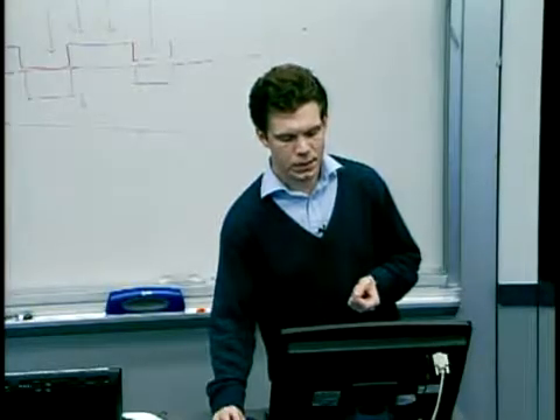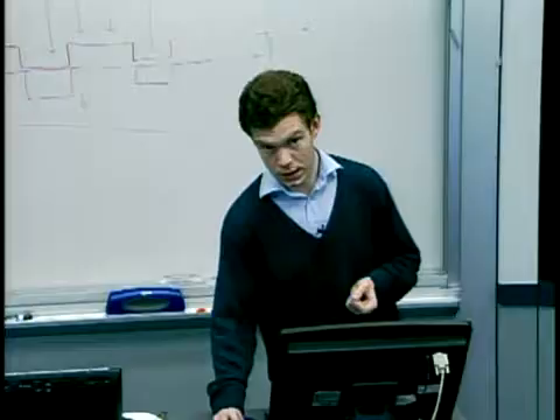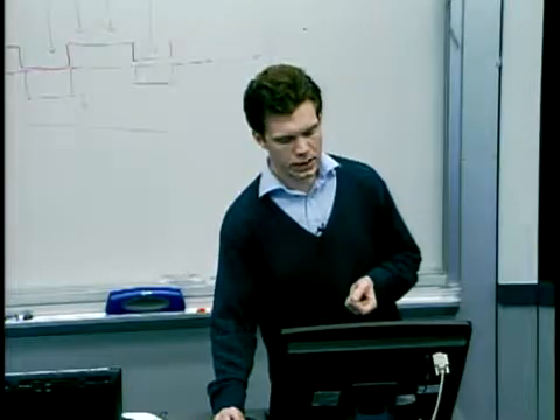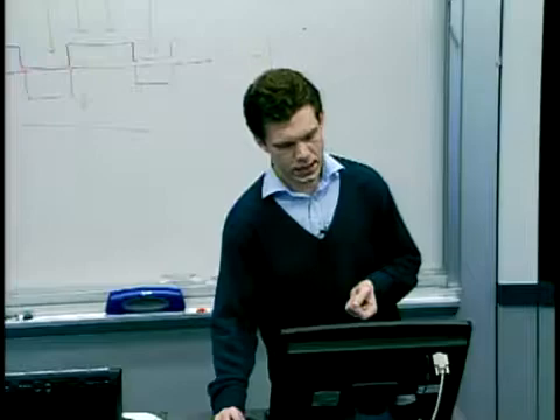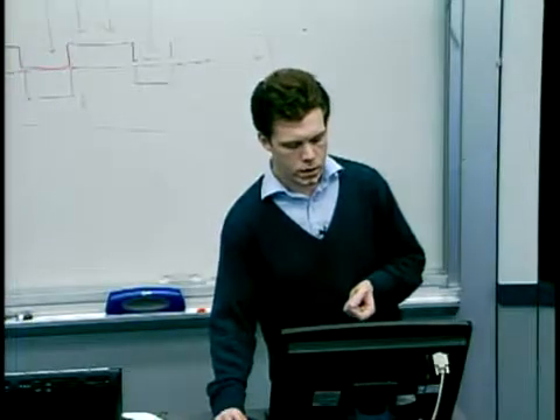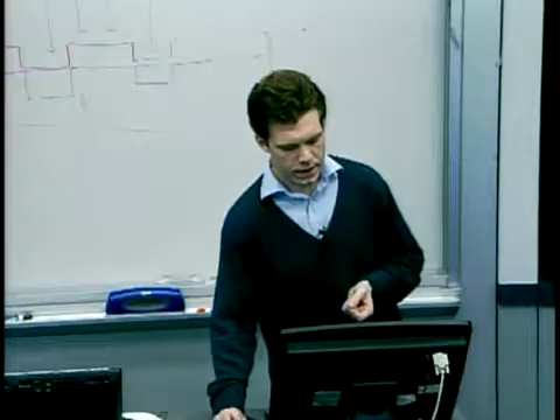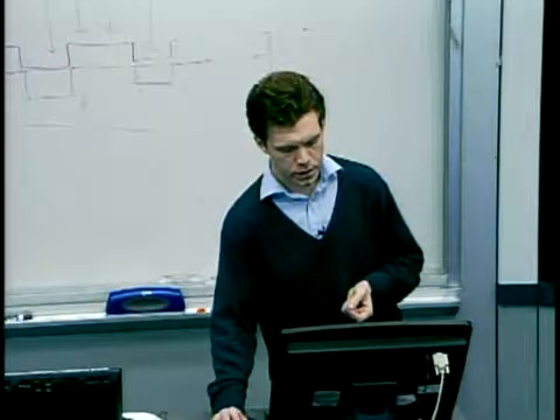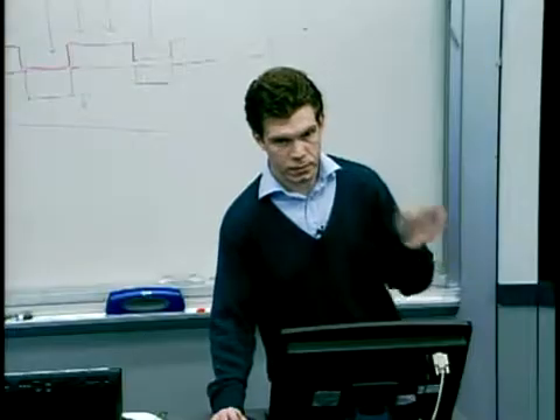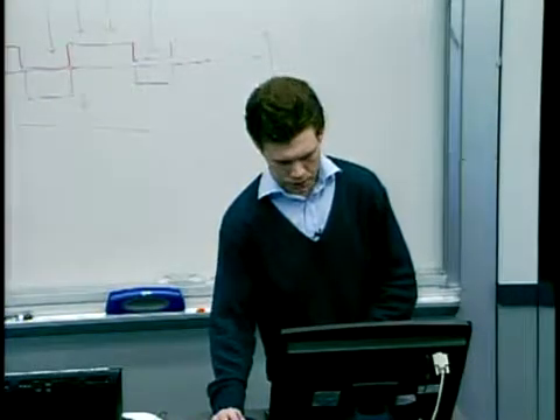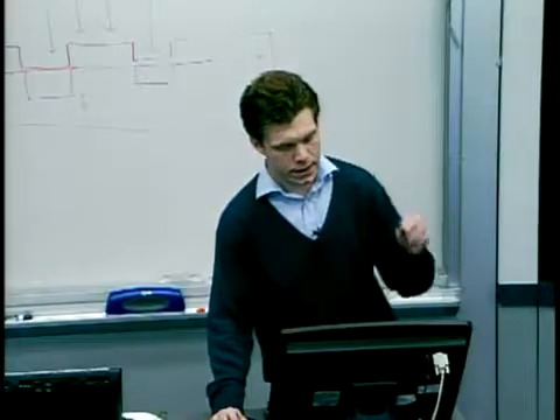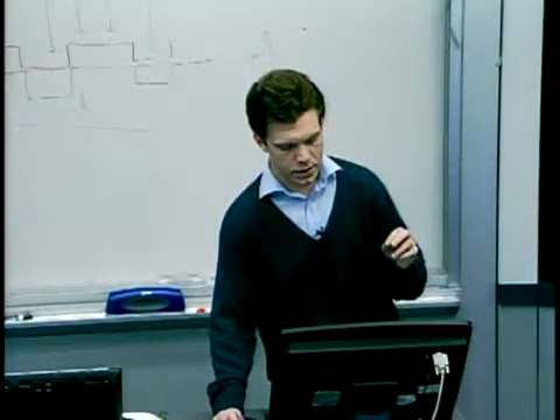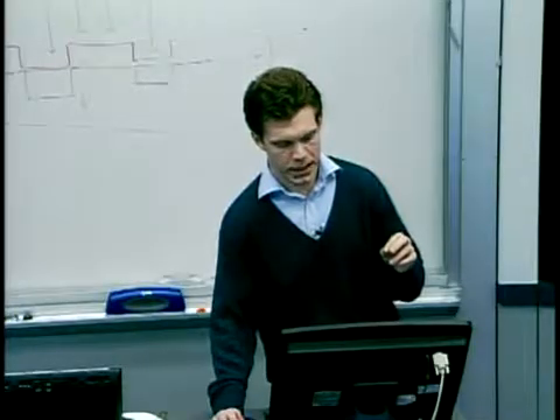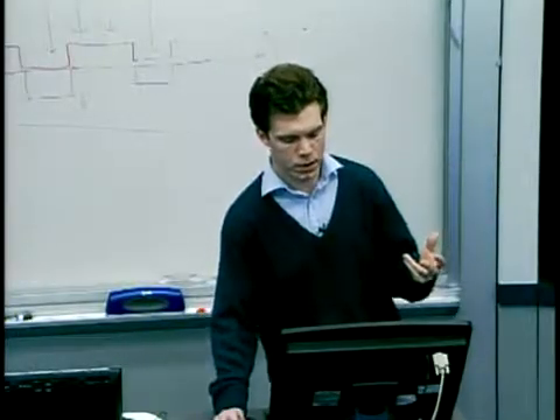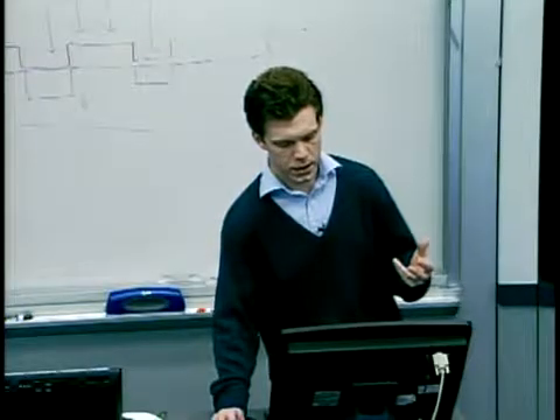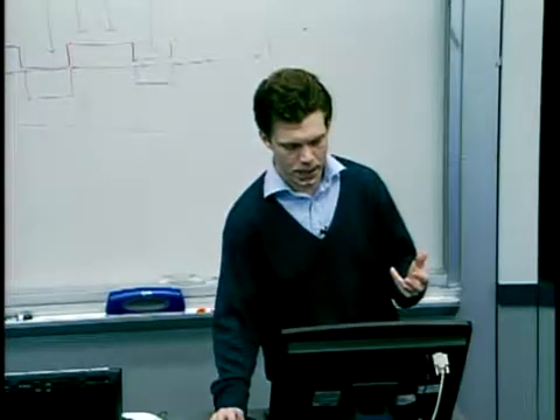That load is maintained while the temperature is reduced below glass transition. Glass transition here is about 105 degrees C. So then we looked at how the model responded to that. There's a compressive strain, of course. There are stresses built up in the left-hand branch of that model, this spring and this dashpot, and there are stresses in the right-hand side as well. And essentially what this shows is that most of the deformation is frozen in place, frozen by this cooling below glass transition. So when the load is removed, this amount of strain remains, this P amount here.